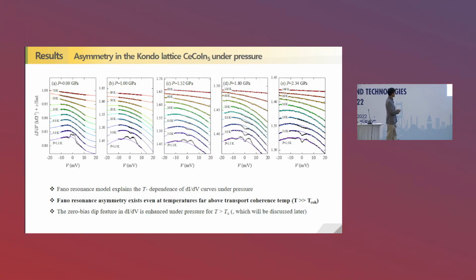And the other thing is that in all pressure ranges that we studied, the Fano resonance asymmetry exists even at temperatures far above the transport coherence temperature. And then also at the 1.5 Kelvin that we reached, the zero bias, and then at a little bit higher than the TC, you may see some of the dip appears, which we will discuss later.